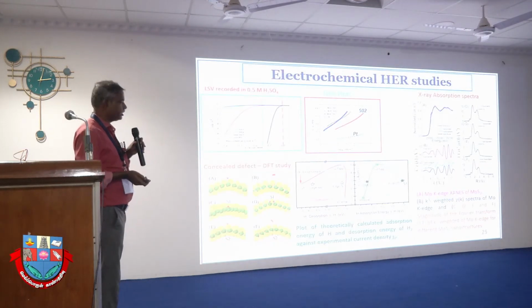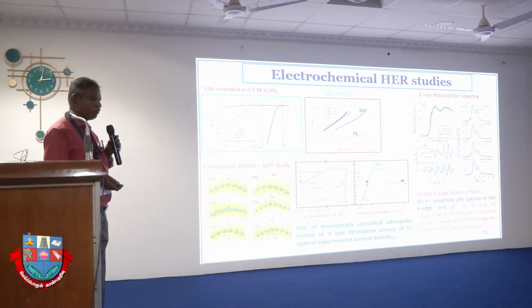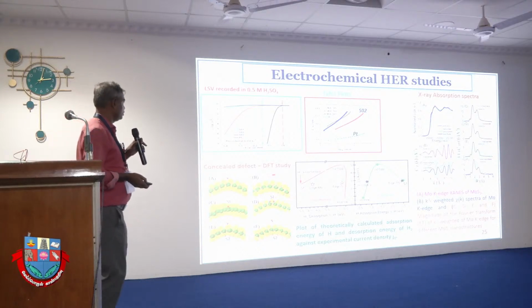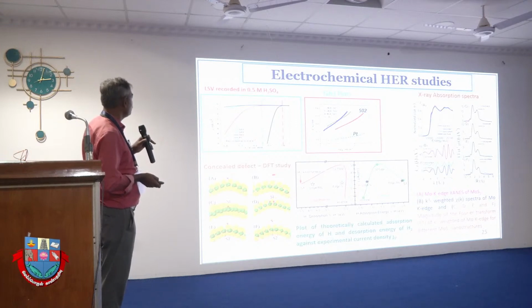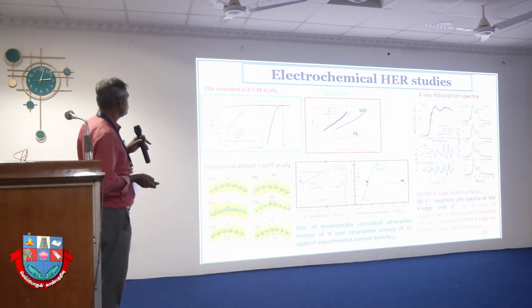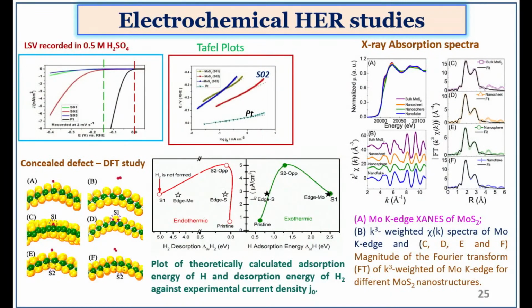So if you go for electrochemical HER analysis, we want to compare with our pure platinum electrode, which starts around 0 volt. But when you go for a morphological change, especially S02 gives an onset potential of around 150 millivolts. So the other two, S01 and S03, the nanoflakes and the nanosheets, are not that active for HER. You can see that. So it reflects in the Tafel plot, where platinum gives a very good Tafel slope around 35 millivolts per decade, but S02 gives around 40 to 50. But the other S01 and S03 are not that good. So what it says is that the surface area directly improves the activity.